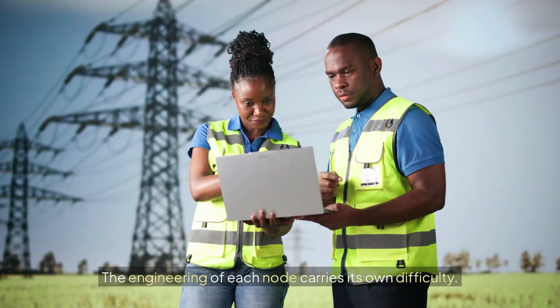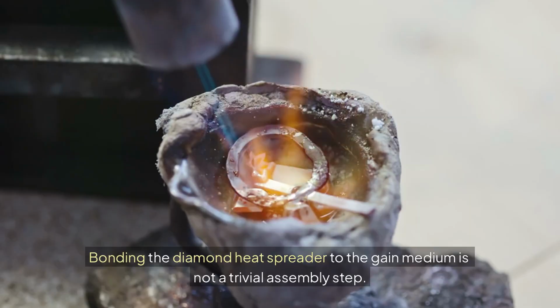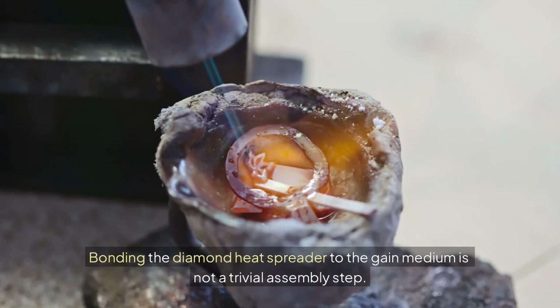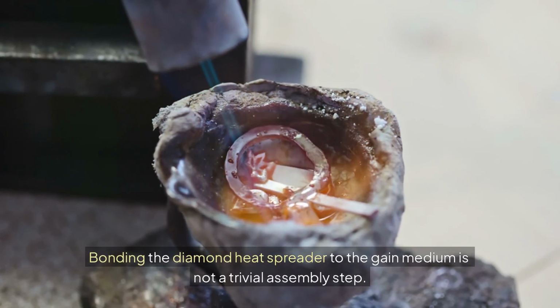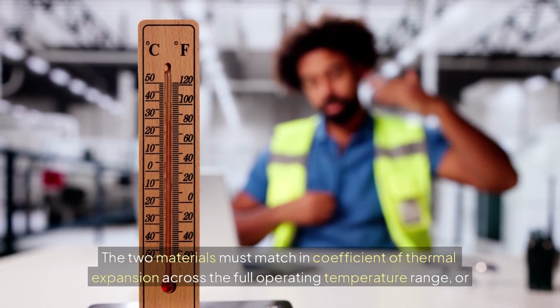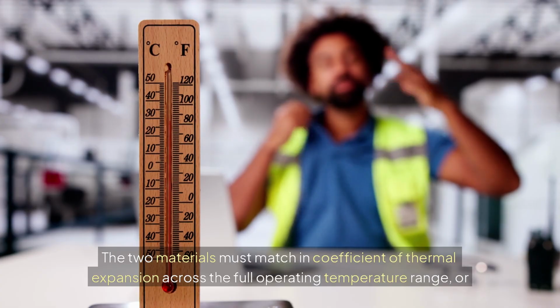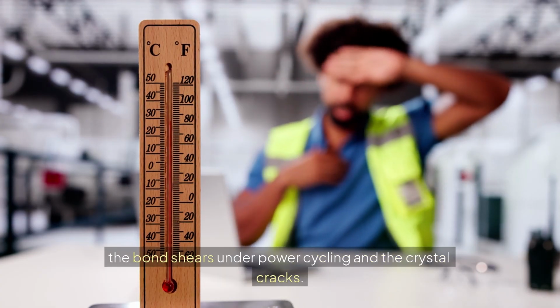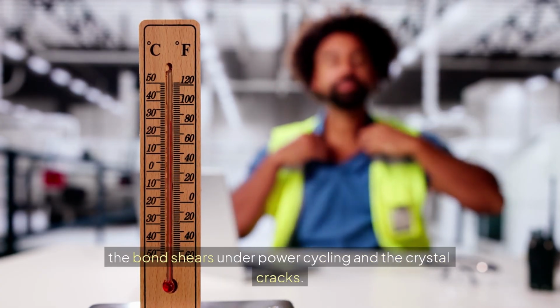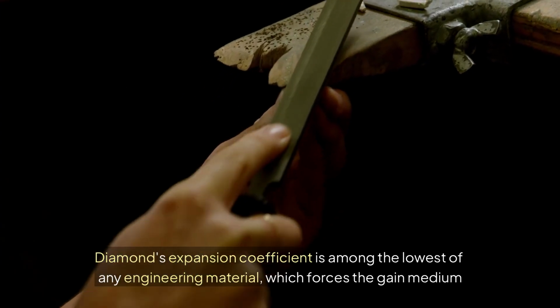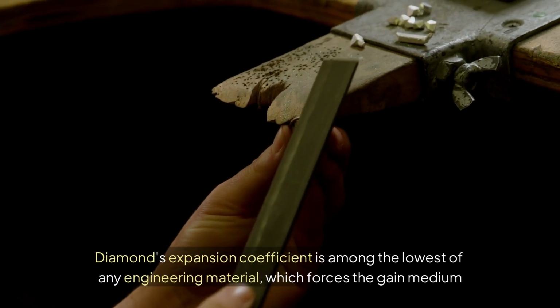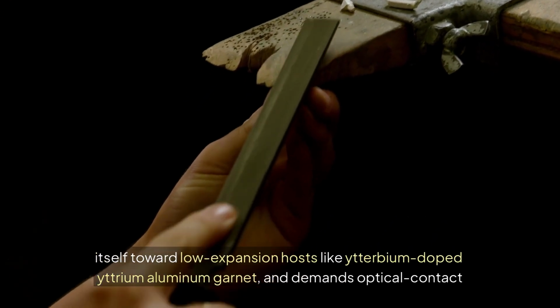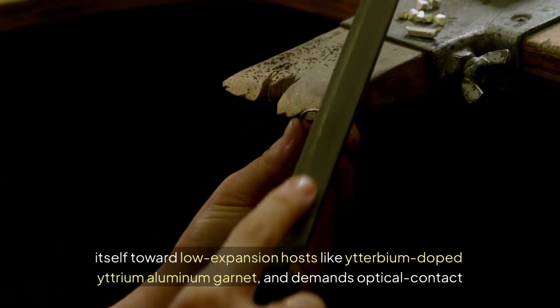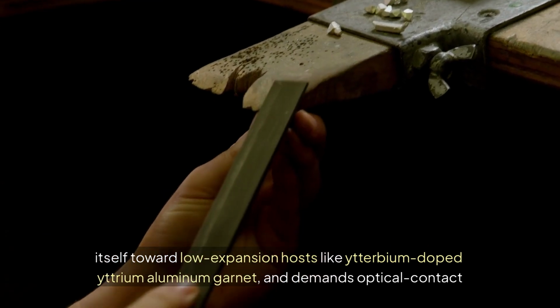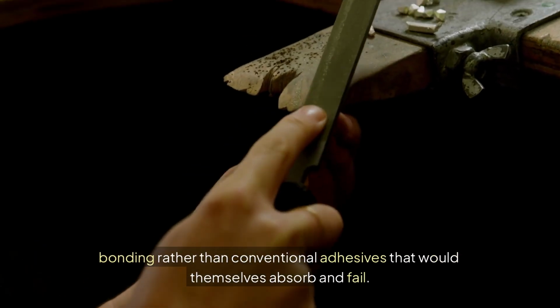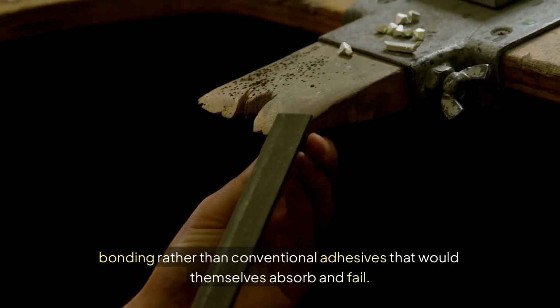The engineering of each node carries its own difficulty. Bonding the diamond heat spreader to the gain medium is not a trivial assembly step. The two materials must match in coefficient of thermal expansion across the full operating temperature range, or the bond shears under power cycling and the crystal cracks. Diamond's expansion coefficient is among the lowest of any engineering material, which forces the gain medium itself toward low expansion hosts like ytterbium-doped yttrium aluminum garnet, and demands optical contact bonding rather than conventional adhesives that would themselves absorb and fail.